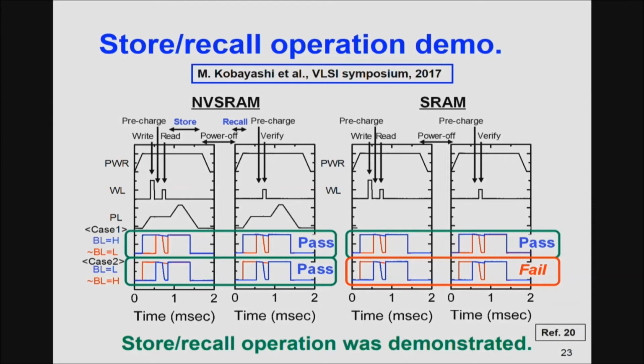What we did was first write data 0 or 1, precharge the bit line, and read the data for confirmation. Then we store the data before power off and wait an arbitrary time during the power off. When we power on, we recall the data, precharge the bit line, and verify the data. From these results, we were able to perform store and recall operations in the NVSRAM. On the other hand, the SRAM just erases the data when it's powered off, and when powered on, it becomes a state which is determined by the characteristic variability. So this is a demonstration of an NVSRAM with ferroelectric hafnium oxide.